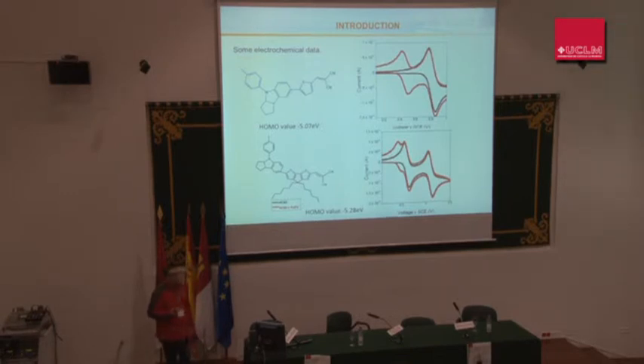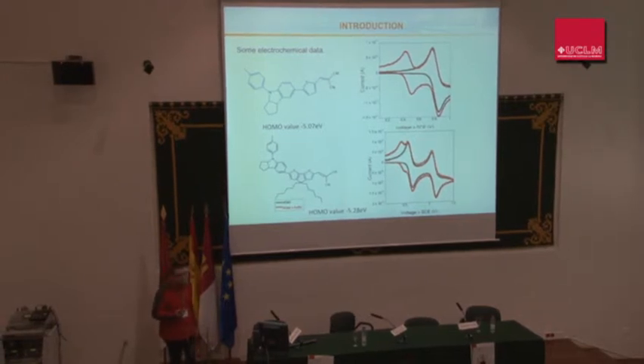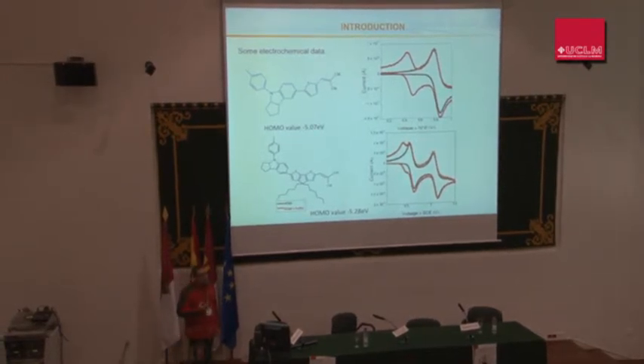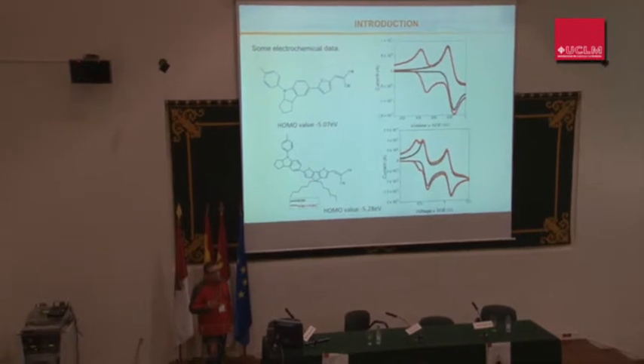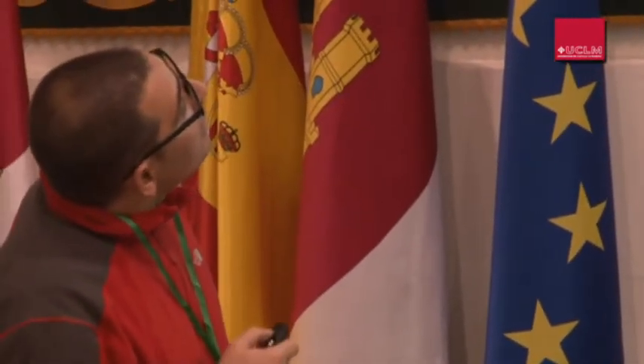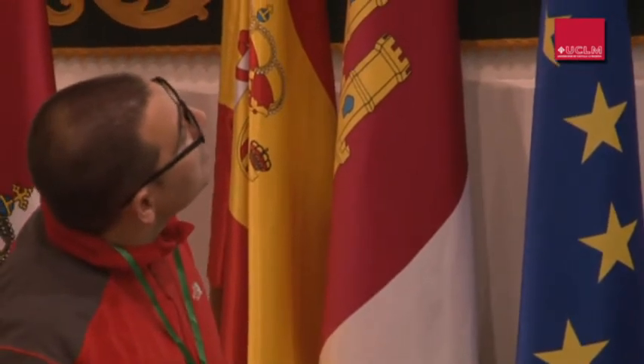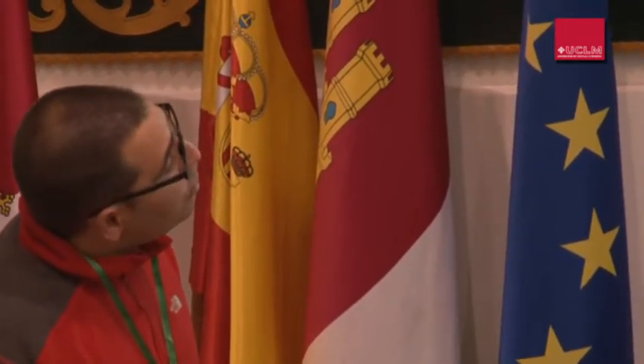If you have worked with polymers and tried to do electrochemistry on them, you will find that finding electrochemical ways to measure them is extremely difficult. In small molecules, it's rather easy. You can fully oxidize these molecules and get the HOMO. And if you use ferrocene, you can refer this to the vacuum level, so you can have a good approximation of the electronic gap of these molecules, and you have to be very careful with that.